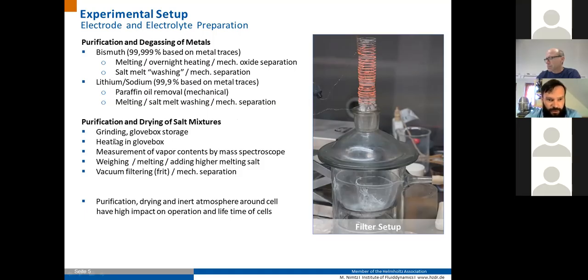are typically prepared in the second glove box. There the steps are to grind the raw salts, solid salts, to store them in the glove box to have a low moisture level, and then there is a heating procedure over several hours up to days to remove moisture mostly. And the vapor contents are measured by the mass spectroscope to get an idea what was included as impurities in the moisture or in the salt mixture.